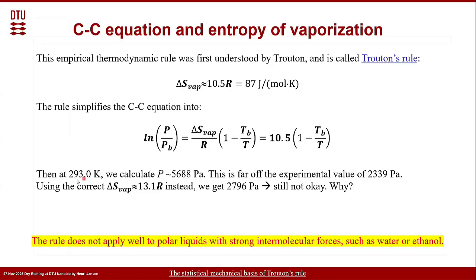Now, for instance, at 293 Kelvin, we calculate that the vapor pressure is 5,688. Wow, that's really far off from the experimental value of 2,339 Pascal. We should have used the real value for water for the entropy of vaporization, and for water it's just completely different. We would have gotten 2,796 if we had used this number. Still not okay, but why does this happen?